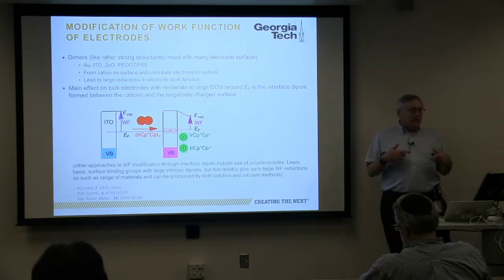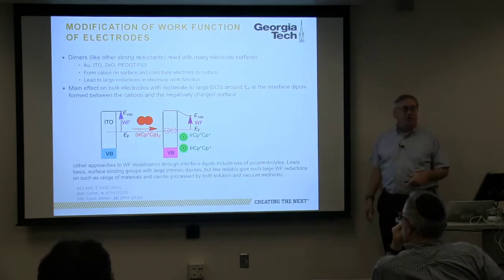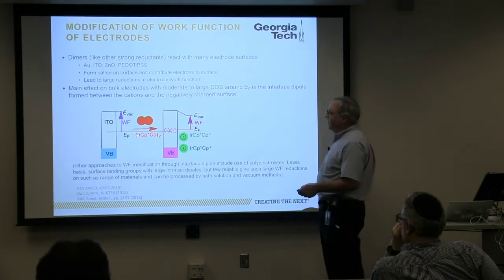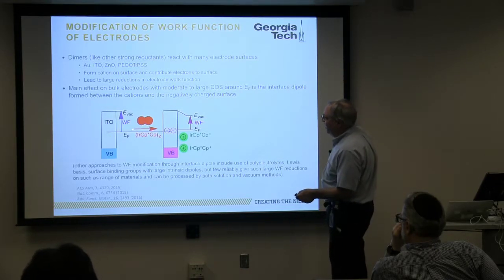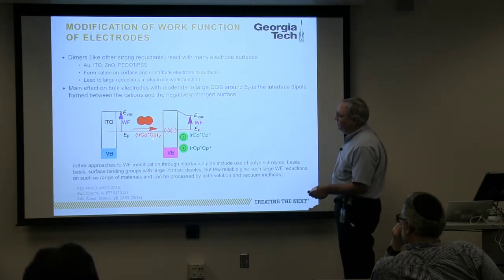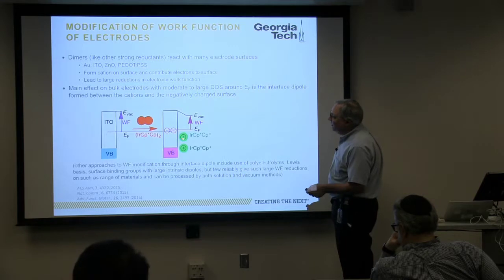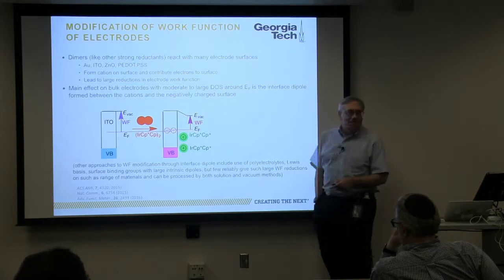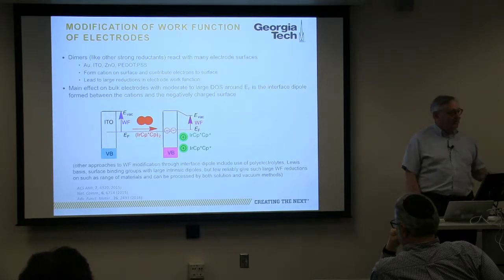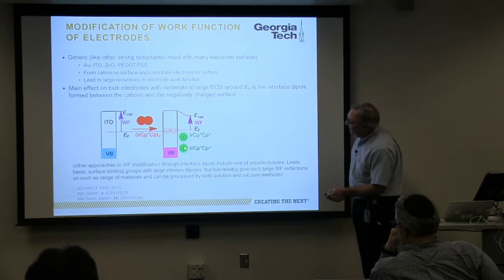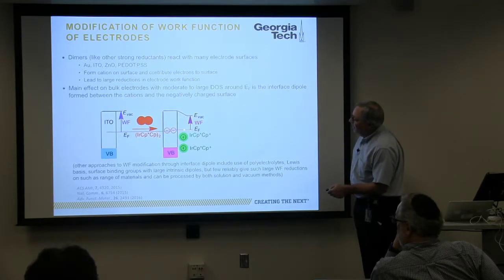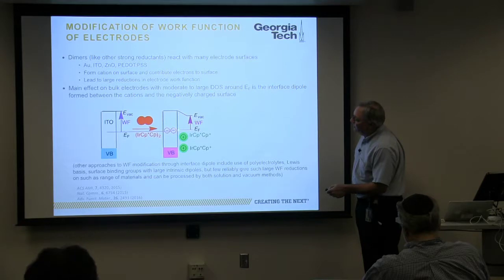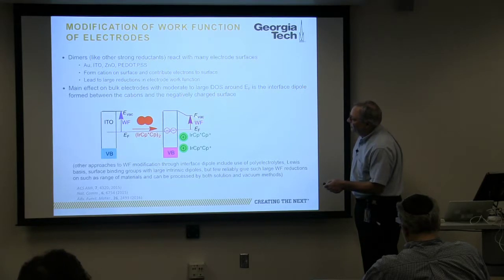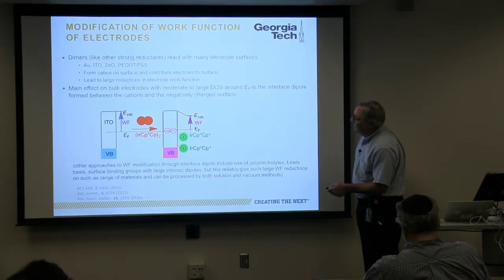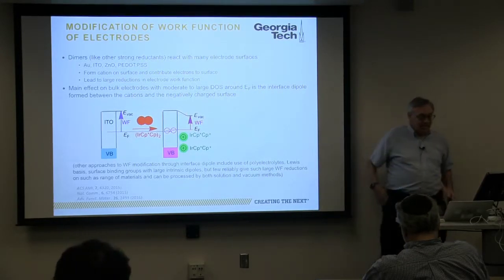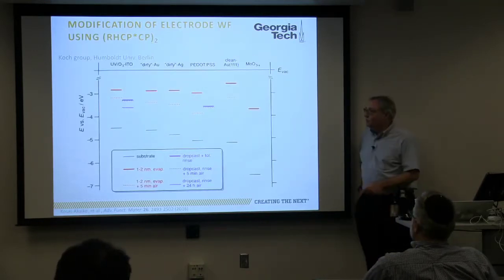You can use these dopants to modify the work function of materials. So let's assume you have something like indium tin oxide that has a work function. And then we react it with something that is a strong n-dopant. At the interface, what we can do is dump electrons into the ITO. When we do that, we oxidize the material, and then what we end up putting is cations right on the surface. And what that does is it creates something that's called an interface dipole that shifts the vacuum level, and as a consequence, the work function goes down. So let's see what you can do with this.